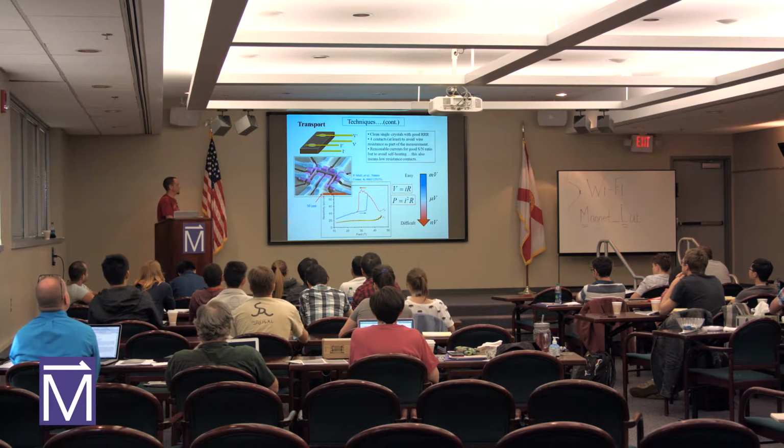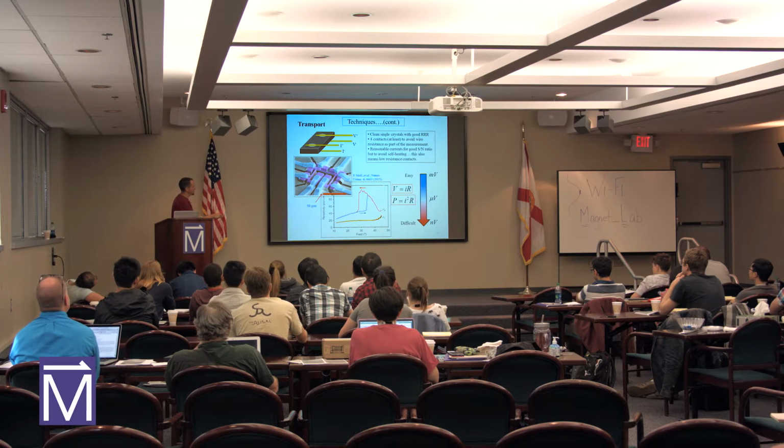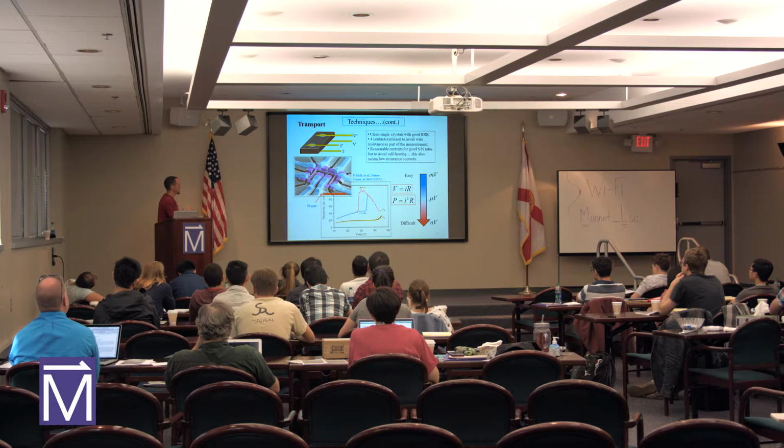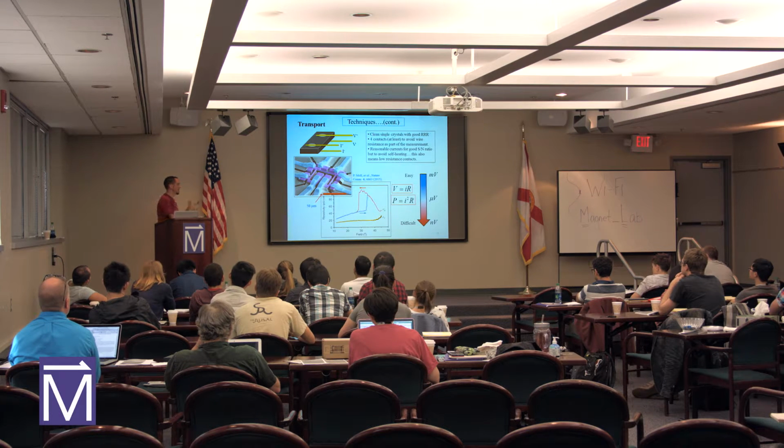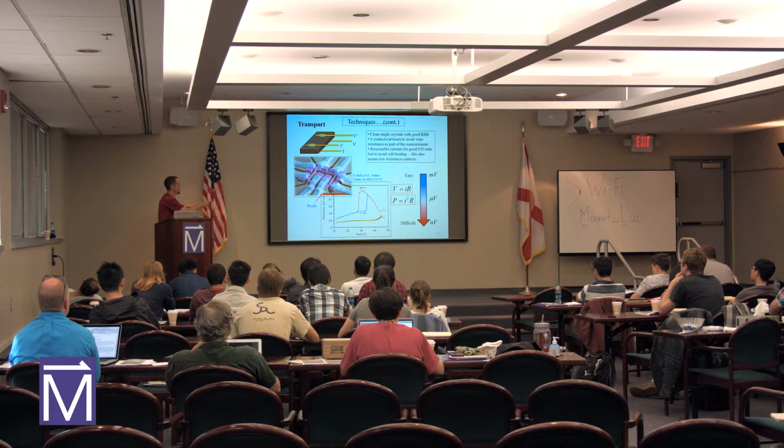But a guy who's worked pretty often with the MagLab, Philip Moll, has developed this technique where he uses a focused ion beam to basically obliterate most of the sample. You can see the dimensional scale here is 50 microns. He blows away most of the sample and leaves these thin channels to actually measure. From the cross-section of a wire, the thinner a sample, the higher the resistance, which makes it easier to measure. You can also isolate these along crystallographic axes. He might say, I want to know the resistance along specifically the b-axis of the sample in some specific orientation, and he can carve it out this way.